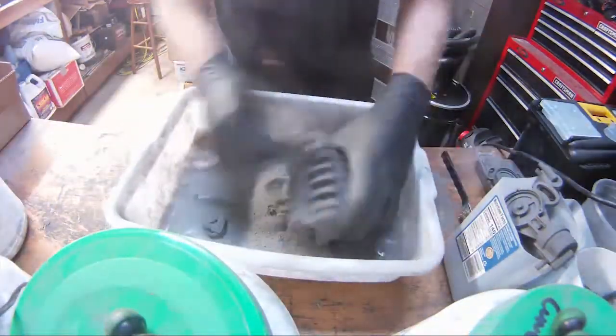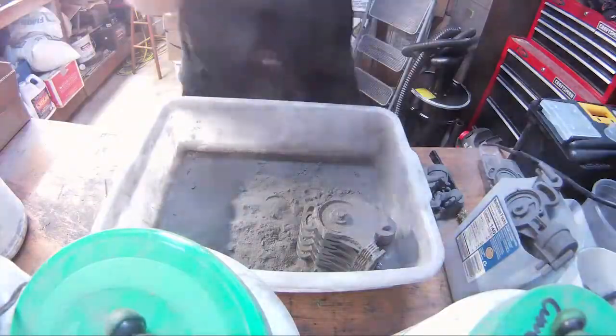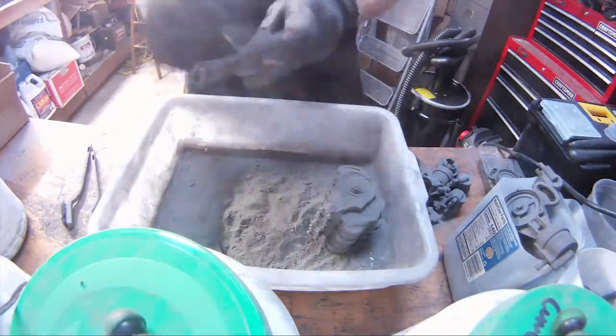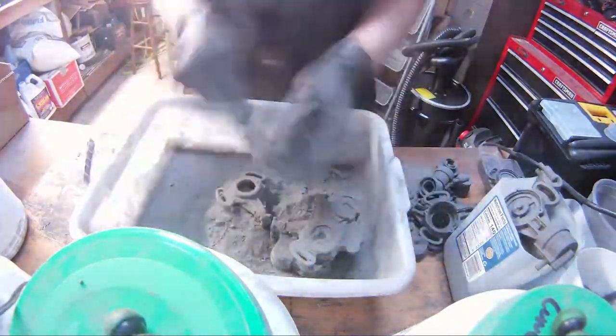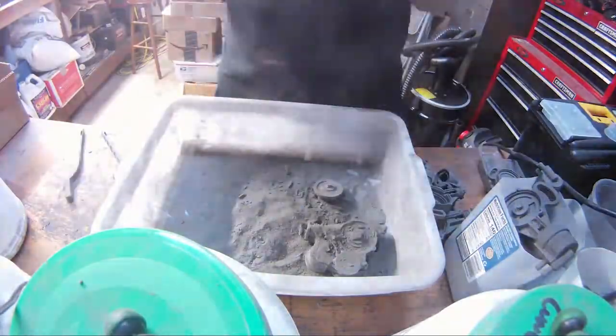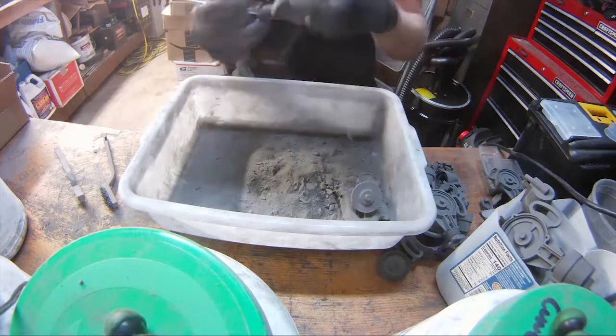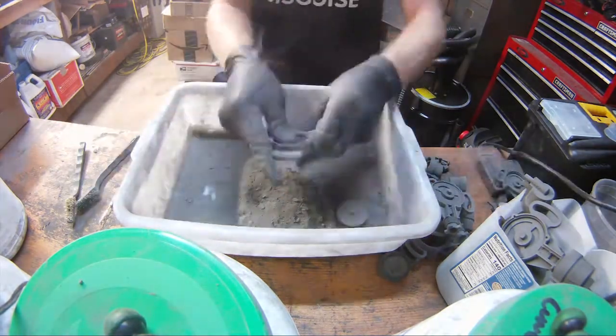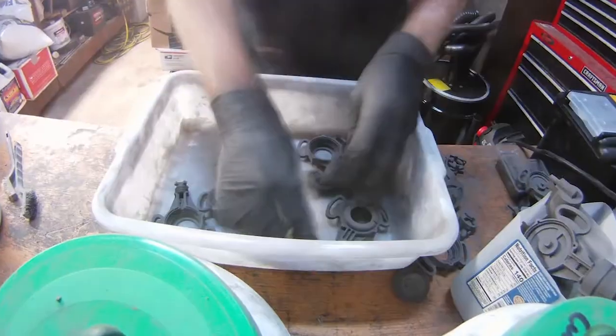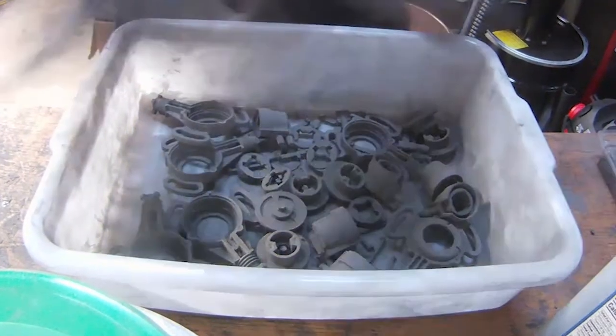Then you excavate it — you basically pull all of the geometry out. When I have something this tightly packed, it's essentially like one element; a lot of geometry in one tiny little place. Some of these things are separated by only a half millimeter, so you just lift the bed as high as it can go, then grab it and pull it out. Right here I'm just scraping away all of the powder. I didn't have any fusion, which is great — my temperatures are just right on. Then you use a toothbrush to clean off any extraneous powder.